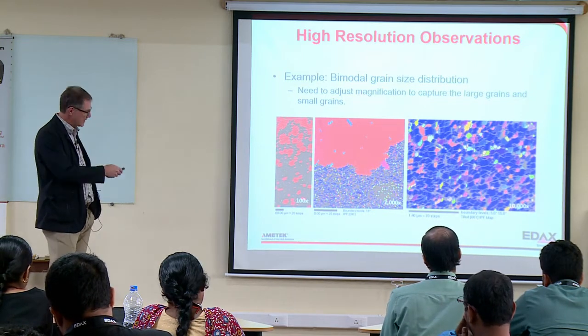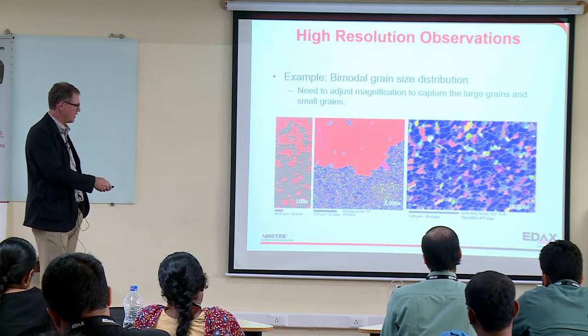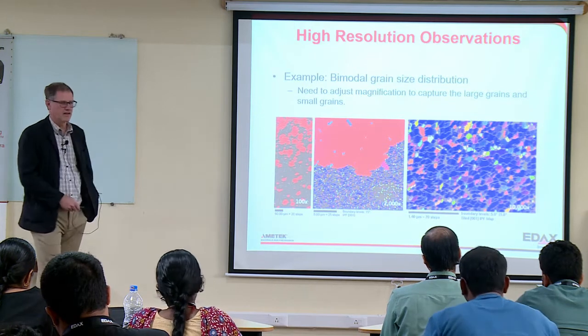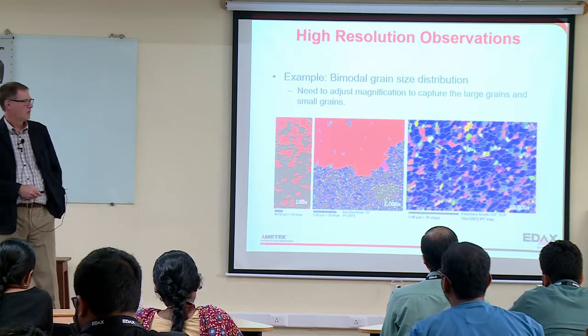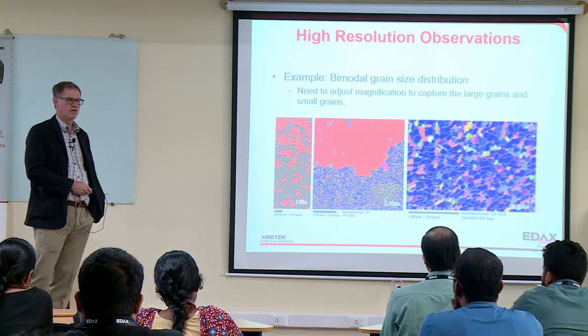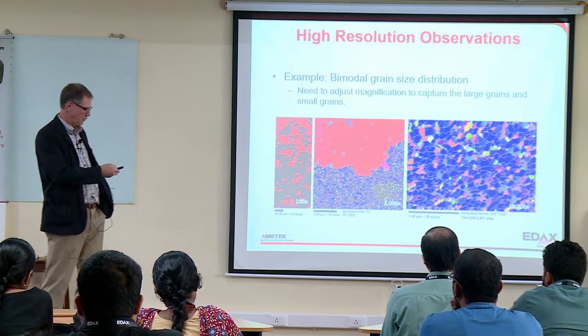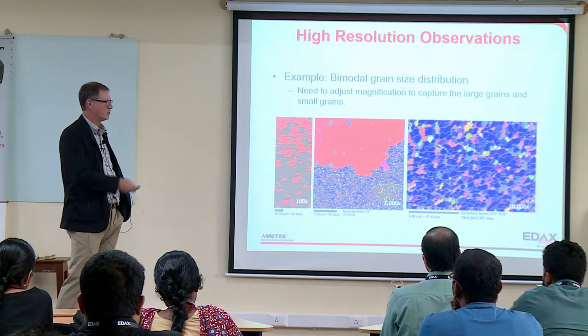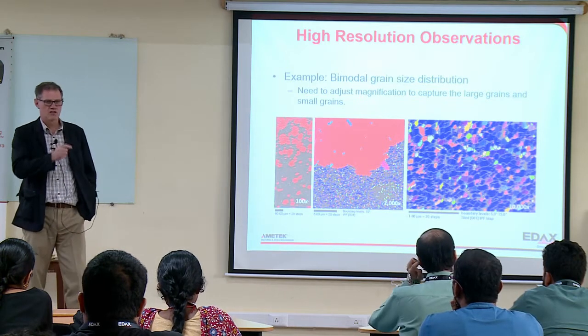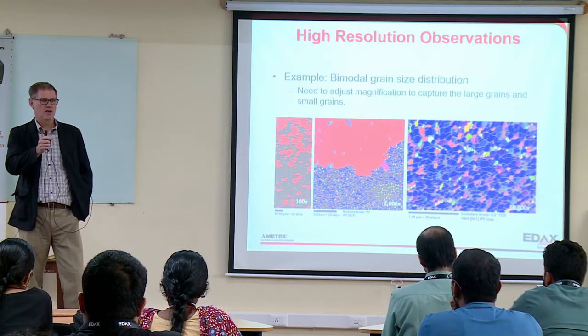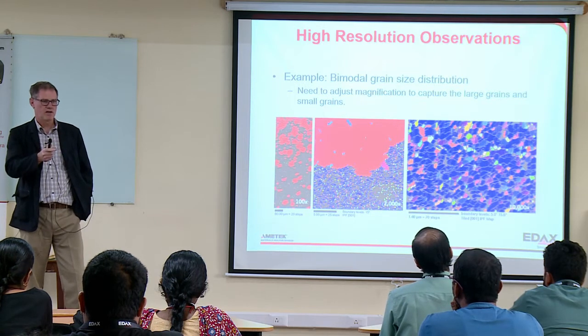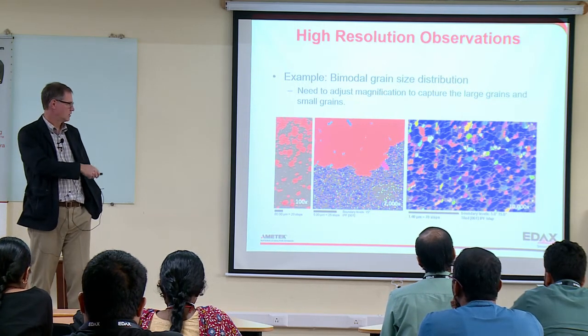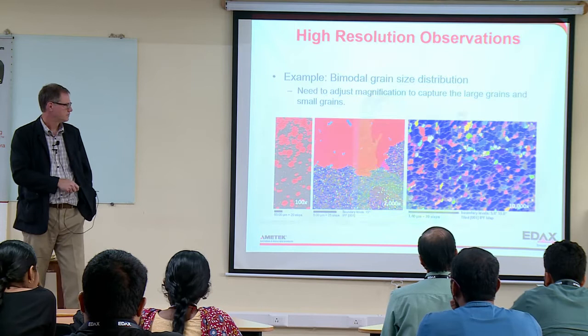So sadly, we can't operate at a low kV and pick up that and the big grains at the same time. And that's why I showed that example from the meteorite. If we want to really capture this whole microstructure, we're going to have to do a beam scan, shift it a little bit with a stage, do another beam scan at high magnification to reconstruct and stitch this all together.